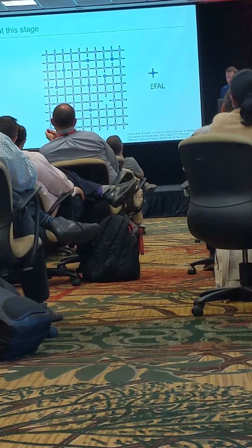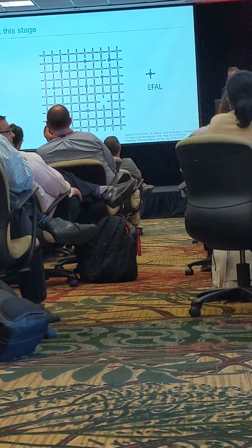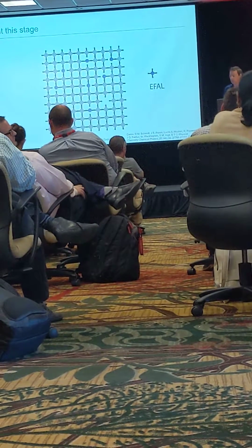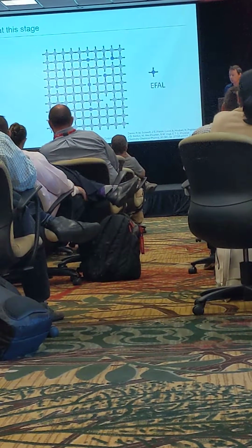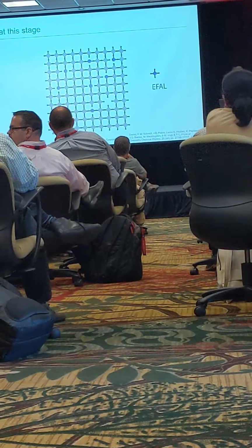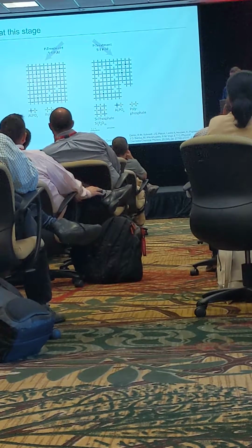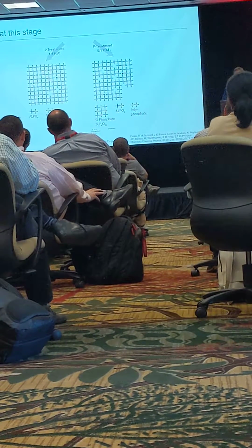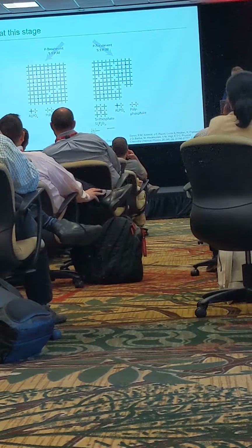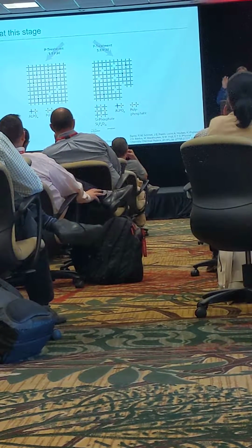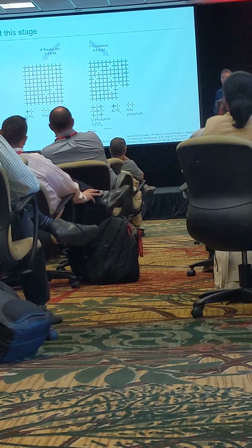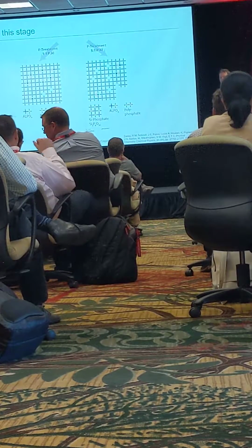Okay, quick snapshot then of the model. We have basically a situation then where we have a ZSM5 with a number of silicon atoms. You have aluminum atoms in here as well. It's been heat treated. We've got some dislodging of some aluminum, and we've got some partially dislodged aluminum species. We do the phosphation, and as we said, you can create some polyphosphate species, some external AlPO species, and then we've also got phosphorus integrating into the framework. You get very high phosphorus loadings. You can actually get entirely different species like these silicon phosphates that we discussed earlier.